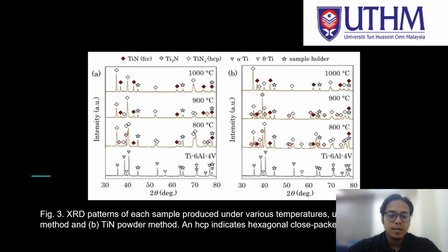Now, figure 3 shows the XRD pattern of each sample produced under various temperatures. It shows that nitride-based phases were synthesized after microwave irradiation. The synthesized phases included two or three titanium nitride phases, which are TiNx, Ti2N, and FCC TiN, and these peaks were shifted compared to the substrate peak. From the Ti-N phase diagram, TiNx was generated when the N content was small, and as it increased, Ti2N and FCC TiN were generated. Thus, nitrogen-rich phases should mainly be observed when the process temperature increases. The intensity of FCC TiN increased with increasing holding temperature in both methods.